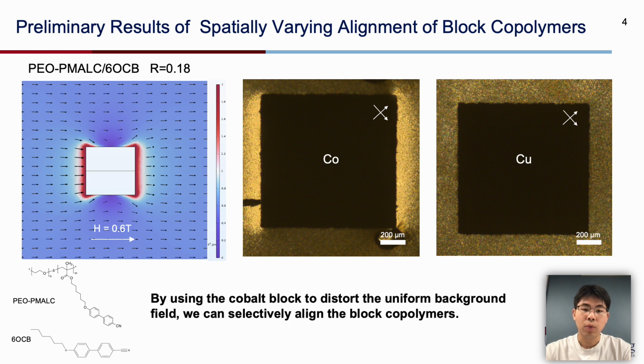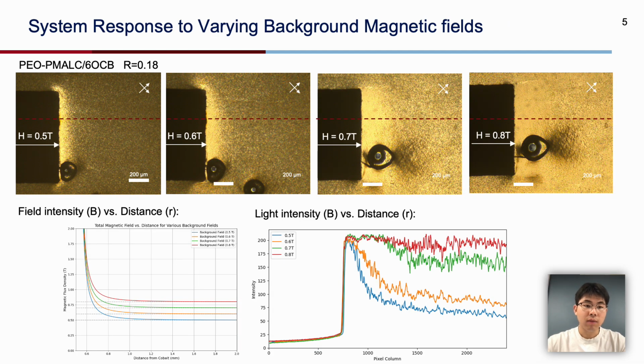We can see with the polarizer at 45 and 135 degrees, the left and right side regions become brighter, which means the material in these two regions is aligned by the strengthened field, but the top and bottom cannot be aligned by the weakened field. We also compare these results with a copper sample. The copper sample doesn't show a brightness change around the copper, which helps us to exclude that this texture change is only induced by surface anchoring of liquid crystal or thickness change of materials. So we can conclude that by using the cobalt block to distort the uniform background field, we can selectively align the block copolymer.